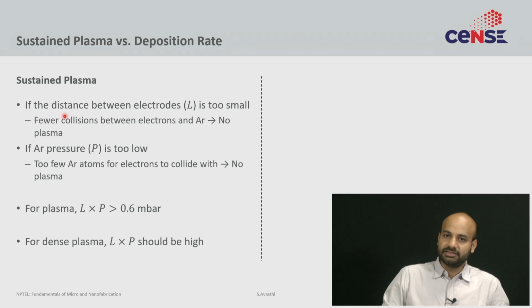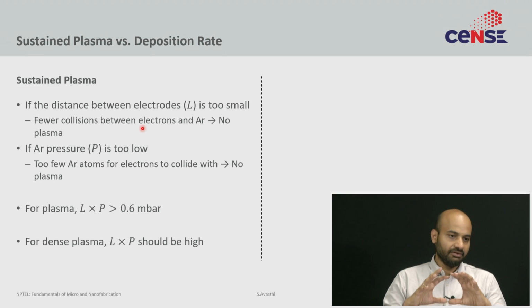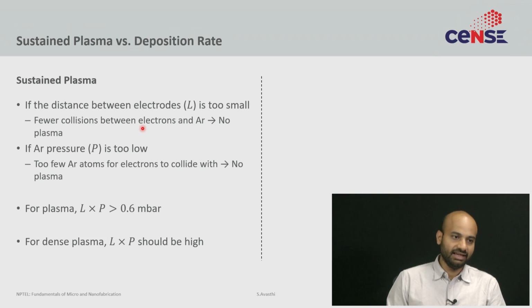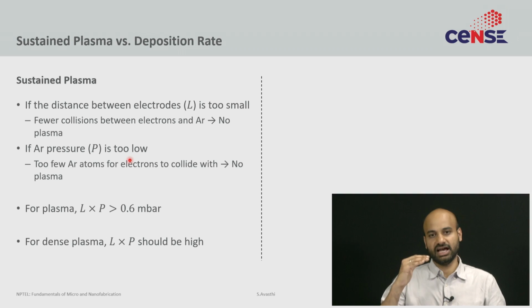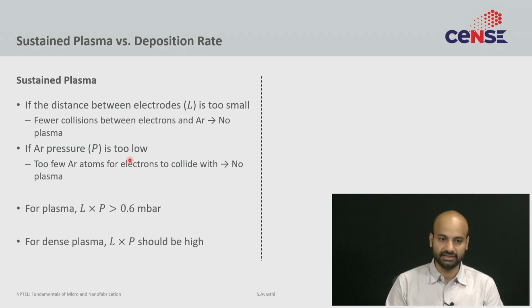So supposing you are doing DC sputtering and supposing the distance between the electrodes is too small, right. Then there are fewer collisions between electrons and argon. If the distance is very small and the gas is sparse enough, it is completely possible that the electron will not encounter any argon atom and hence not do any ionization. If however the argon pressure is too low, again the same problem. Even if the distance is large but the argon concentration is very low because the partial pressure of argon is very low, even then the electron may not encounter an argon atom and hence not cause any ionization.